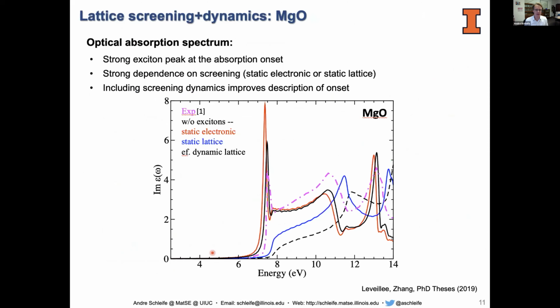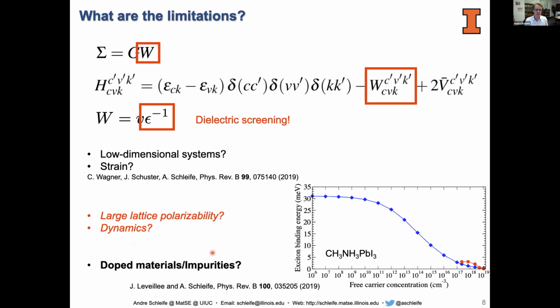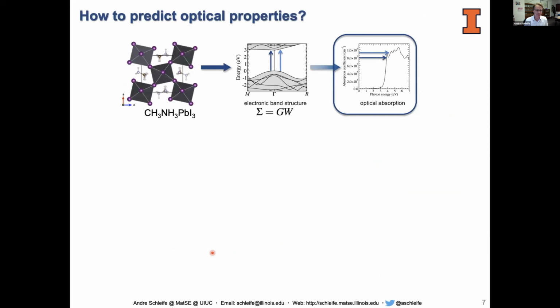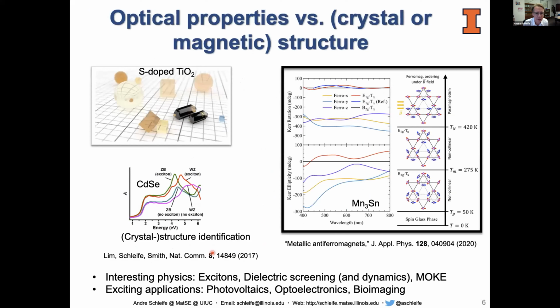So I don't think we looked at the anisotropy for this material. I'm trying to jump back to this one. Is that the slide that you're referring to, right? That material, of course, is known to have properties determined by the Weyl points. It's a Weyl semi-metal, and it has this enormous Hall effect, which is highly anisotropic, as is the Kerr signal. And I just wondered what that Kerr rotation corresponds to, which orientation? I'd have to look back at the paper actually. I think in this case we reported one orientation in the material, and that is in the paper, but I cannot remember off the top of my head.